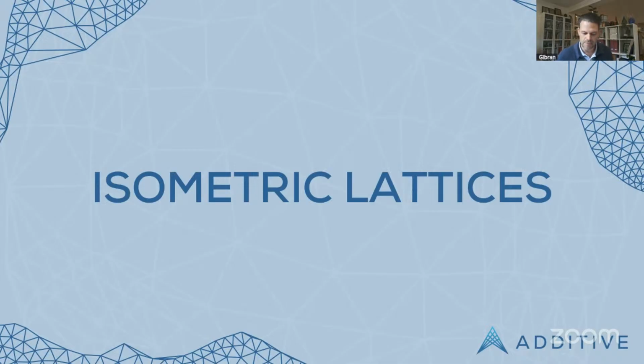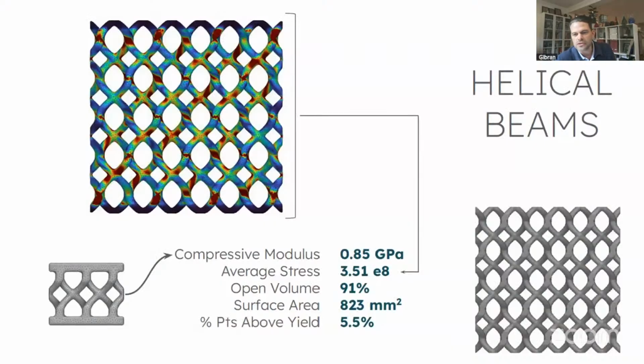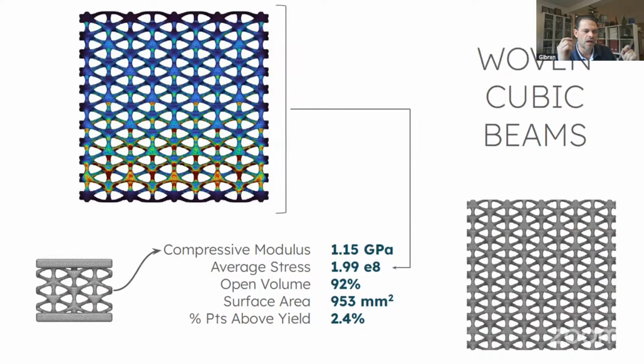It's 3D printed titanium. But looking through some of these lattices when we were doing a deep dive into it, we noticed a few things, right? The modulus of elasticity can be quite good, but then when you put a big frame around it, the modulus changes and it becomes a little bit stiffer. Some of the other repeating isometric lattices, you couldn't have the irregularity of pore size. So something that the clinical team was driving is being able to have irregularity in pore size, like trabecular bone, right? That's not a standard repeating isometric lattice. That has smaller pores and bigger pores. So this is where we really wanted to head.